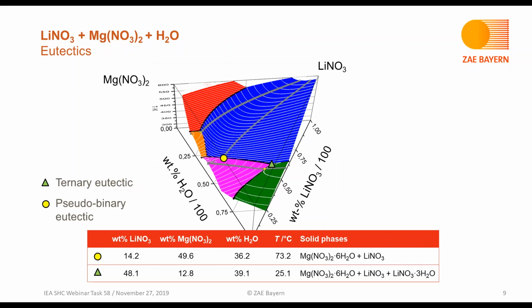In this system, two types of eutectics occur, ternary eutectics and so-called pseudobinary eutectics. For the calculation, the result is the composition and the temperature of these eutectics, as indicated in the table at the bottom. For the pseudobinary eutectics, we have two solid phases in equilibrium with solution, and in the ternary eutectic, there are three solid phases in equilibrium with salt solution.